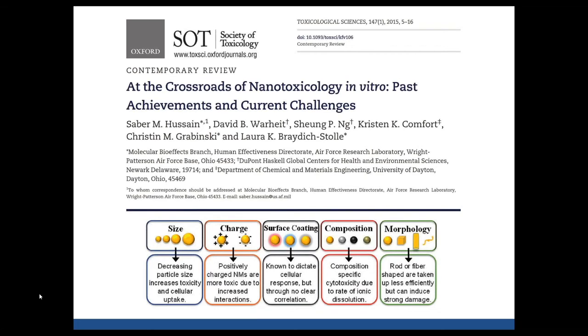From a composition perspective, if there was a rate of ionic dissolution and those ions were toxic, there was definitely a correlation between that and the ultimate toxic result. And in morphology, rod or anisotropic shapes were taken up less efficiently, but once they were there, they could introduce more significant damage. The reason why this is so important is twofold.